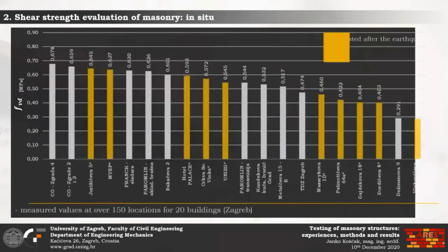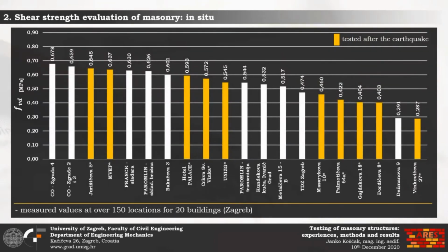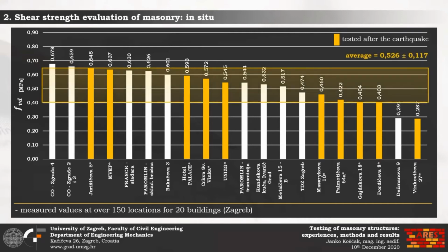This slide here shows the average test results of shear strength measurement for 20 different masonry buildings in Zagreb, measured at over 150 locations. Each bar on the chart represents the average value of all measurements taken within the building labeled below, and yellow bars on the chart represent the measurements which were performed after the recent earthquake. Finally, the global average value of all tested buildings is 0.53 megapascals.